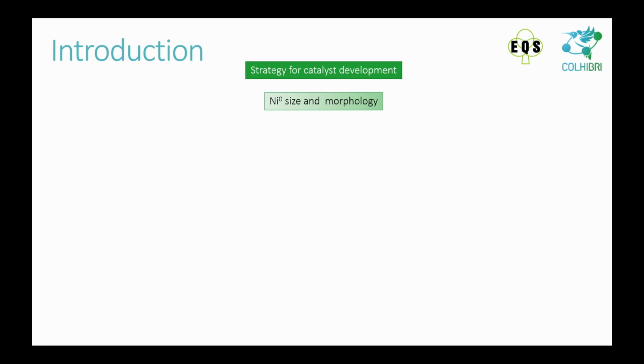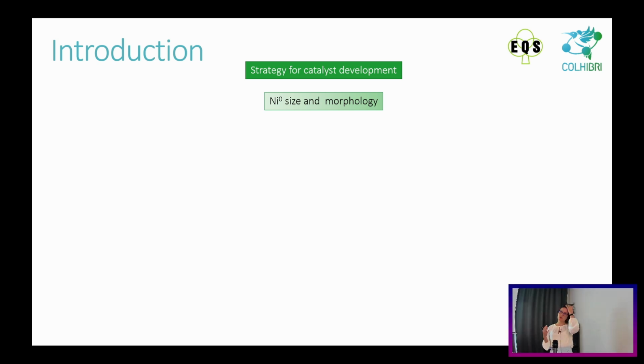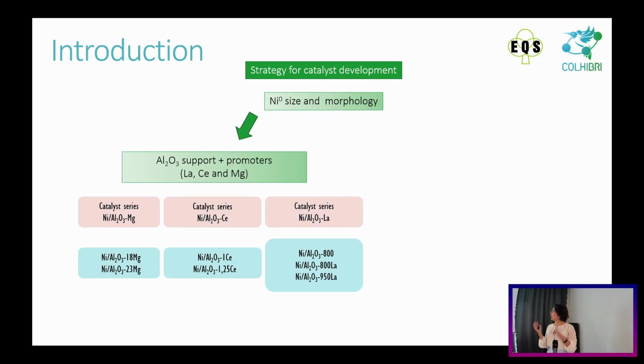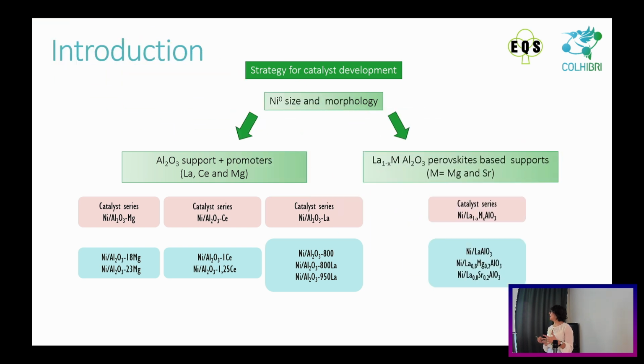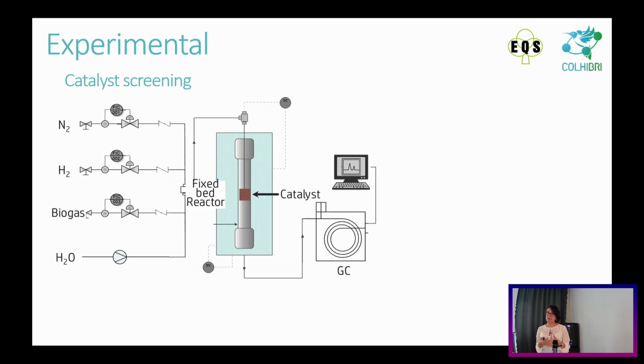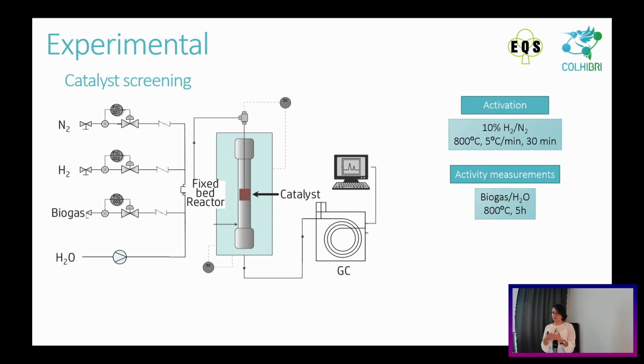So what our group has been working on is the synthesis of nickel-based catalysts on one side with aluminum oxide supports that are modified by promoters such as lanthanum, cerium, and magnesium, and on the other side with perovskite-based supports. And this is all being compared to a commercial nickel catalyst. So the reaction takes place in a fixed bed reactor. And first of all, it undergoes a reduction in H2 followed by the reaction at 800 degrees.